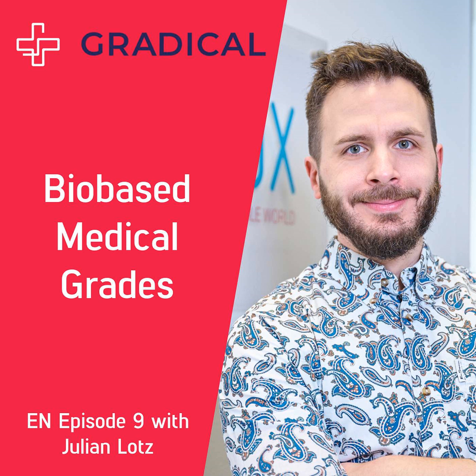But what you also see is that if you want to have a sustainability advantage in the CO2 footprint, you have, let's say, the carbon that you take into the polymer from the atmosphere. So a plant or a bacteria or something like that uses CO2 from the atmosphere to build its molecules. And therefore you absorb carbon from the atmosphere, and therefore you get, let's say, a credit for your LCA. And this credit is usually between 2 and 3 kilograms of CO2 per kilogram of plastic. And this is basically fixed across all types of plastic.